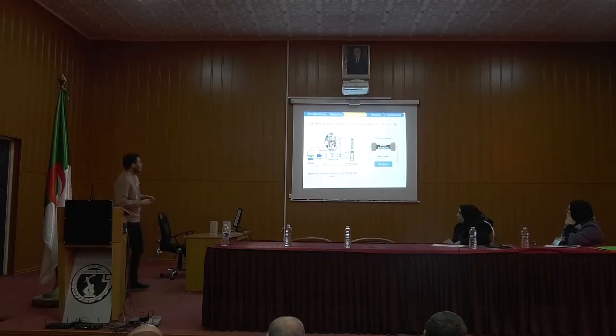So what do we need in flash Joule heating borocarbothermal reduction? We need a power supply, which is a source of current and voltage. We also need a molybdenum tube where the reaction happens. We need a camera to record how the reaction happened. And we also need argon, because this reaction happens under an argon atmosphere. You can see the simplified scheme of the flash Joule heating borocarbothermal reduction: the source, the sample, and the reaction will happen.